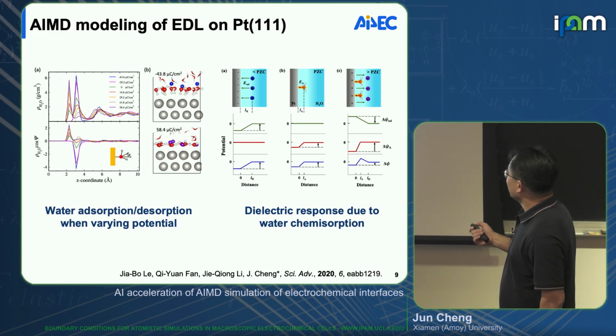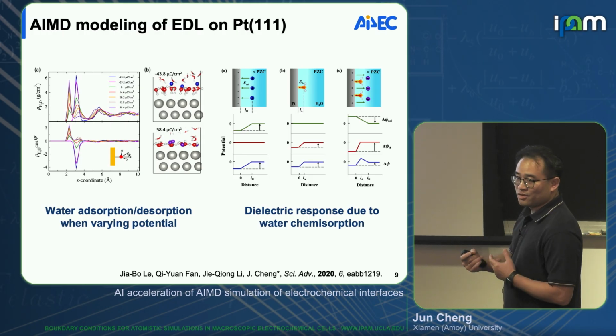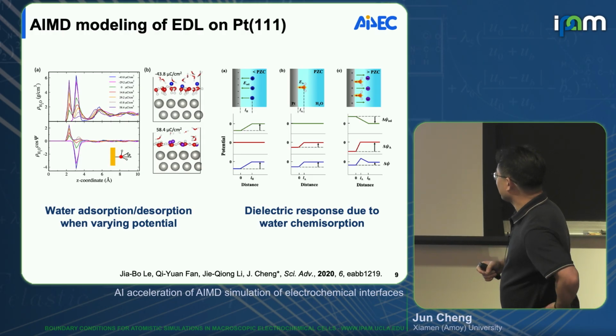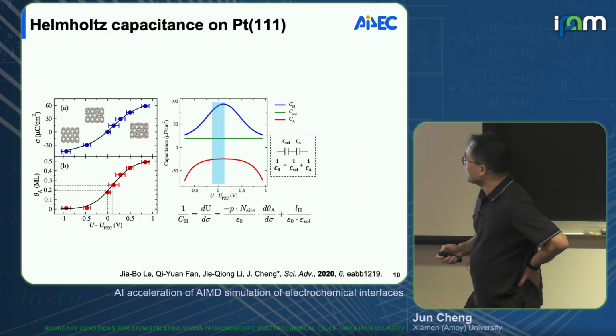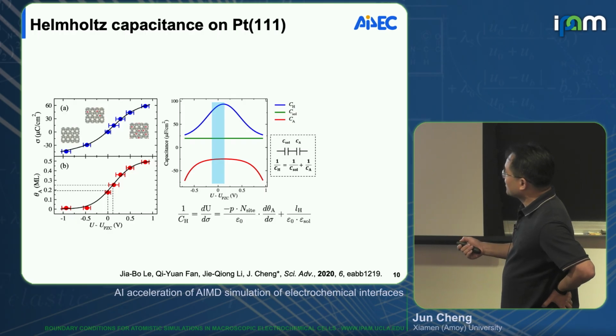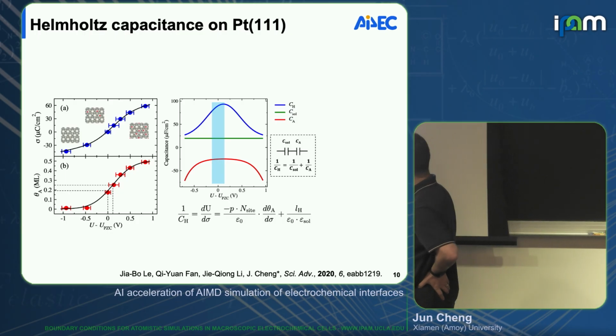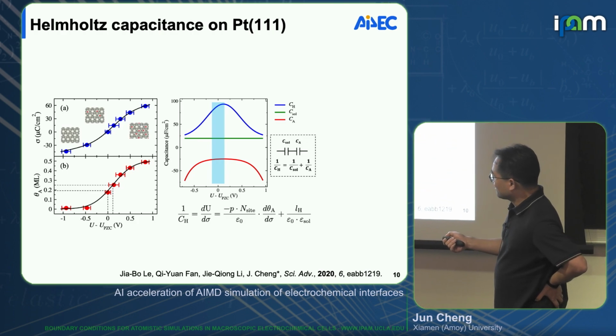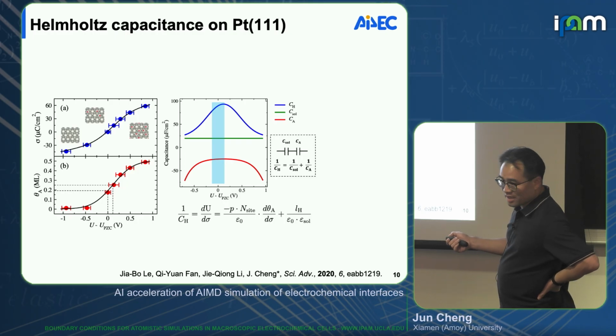When I said water chemisorption, you would imagine there will be a charge redistribution due to this chemisorption effect. So it turns out it will lead to a dielectric response. That's the charging curve, we calculate the surface charge density as a function of the potential, and also the coverage of chemisorbed water. You can also see this S-shaped sigmoid curve. At a very negative potential, where the protons point down, you have no chemisorbed water, and around the potential of zero charge, you have roughly 0.2 monolayer chemisorbed, and it will eventually saturate around half a monolayer at a very positive potential.